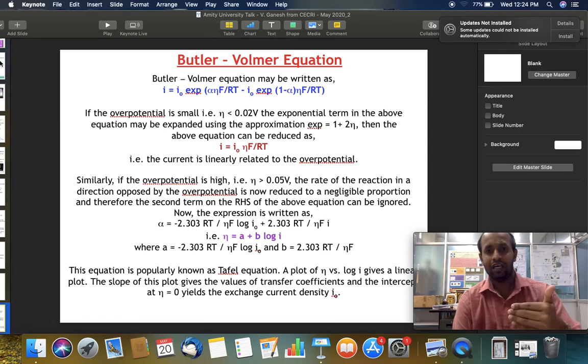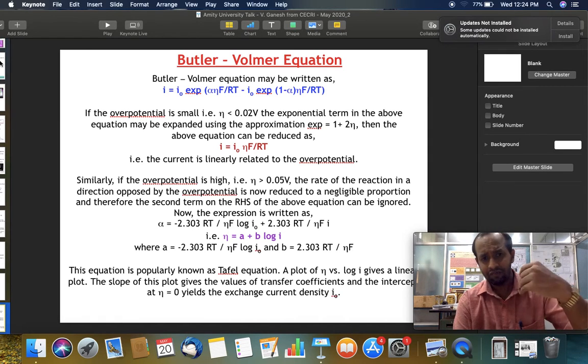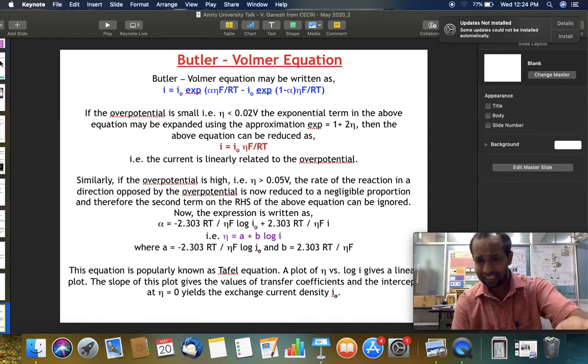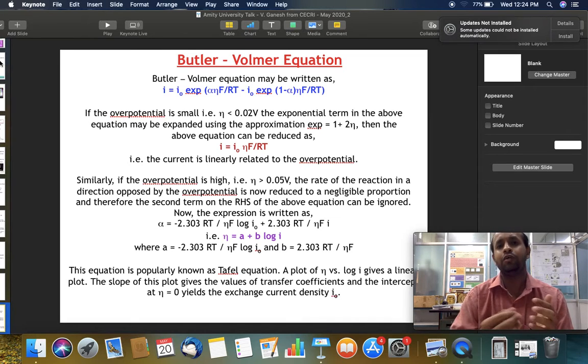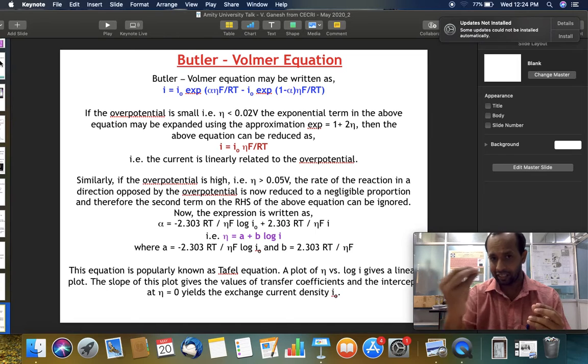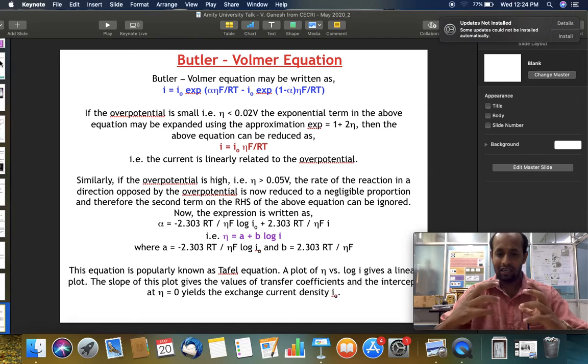Let's say when you apply a very small overpotential of less than 20 millivolt or so, you would end up with an equation of equilibrium like i = i0 η F/RT, where i0 is the exchange current density, which is a very critical parameter to measure in order to understand the concept of current, which arises due to corrosion and electrocatalysis processes.